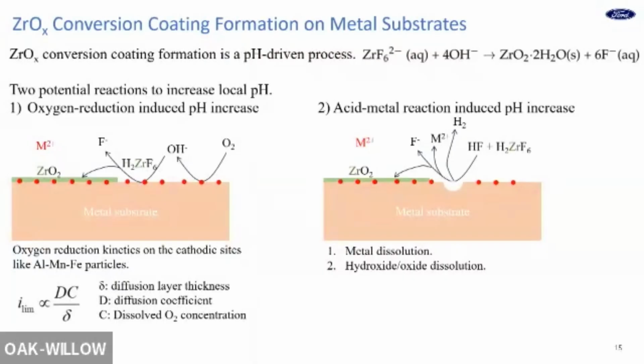Based on the understanding that zirconium conversion coating formation is a pH-driven process, you need a local pH increase to trigger the zirconium precipitates. Now there can be two mechanisms. One is the oxygen reduction reaction: when oxygen is reduced, the pH will increase, and the pH increase will trigger the zirconium formation. Another mechanism is the metal acid reaction. As acid is consumed, the pH will increase, especially for active metal or some coil pretreatment with a strong spray. This mechanism may probably be more dominant, but silicon is not a strong cathode to support the oxygen reduction reaction. Also, silicon is very stable in acid. So how does the zirconium form on silicon?